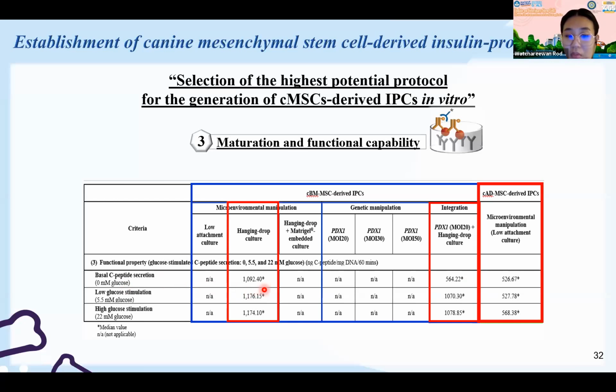So from the basal condition, we found that the bone marrow with the hanging drop shows the highest concentration of the C-peptide among the other protocols. However, when we do the glucose stimulation challenge, starting from the low concentration of the glucose and then continuing to the highest concentration of the glucose, the hanging drop, we found that the C-peptide level just has lower secretion when compared with the low concentration of the glucose.